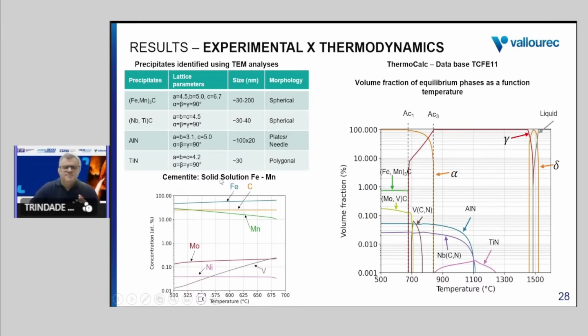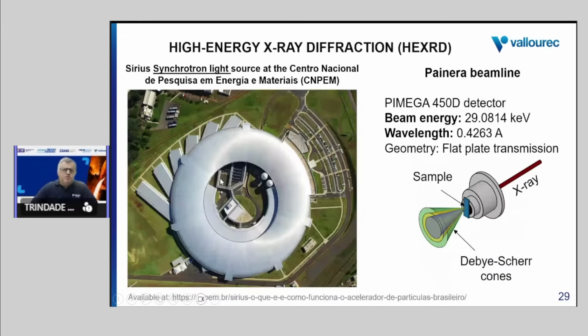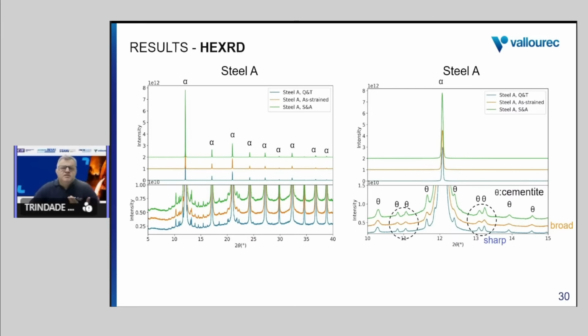Just as curiosity, we also went to a more advanced technique to try to identify smaller precipitates. We used high energy X-ray diffraction. Here in Brazil, we have this facility, located in the São Paulo state, in the city of Campinas. The research center is called CNPEM, Centro Nacional de Pesquisa em Energia e Materiais. There we used this facility to investigate our material in different conditions: as quenched and tempered, strained, and after aging. And what we could observe is, again, nothing,